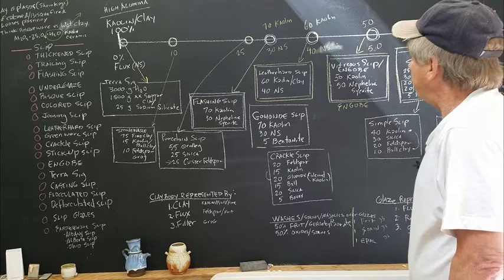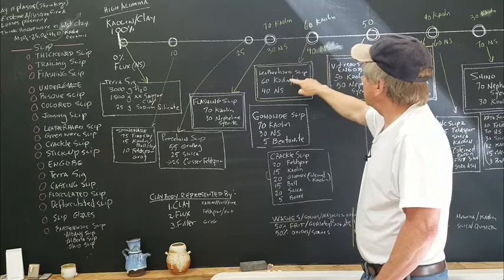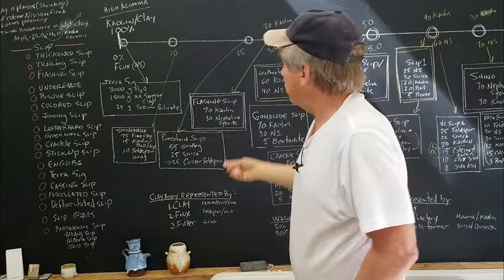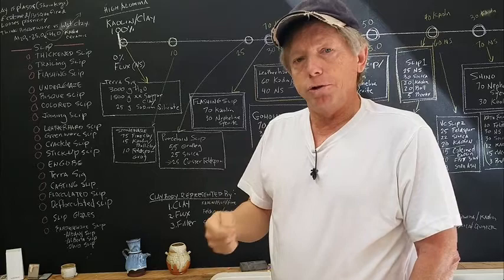All right, so then we'll go to the back a little bit to the leather hard slip. That's like 60 kaolin, 40 nepheline syenite or flux. That's still a lot of clay, 60. But of course it's less than here where it's 80 and 90%. So you put it on leather hard clay, and you can do a lot of decorating before you bisque fire it. That's the idea.